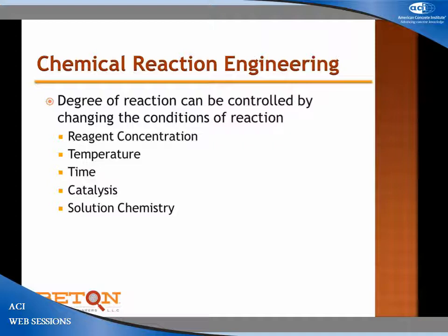So we know all of these things. We know solution chemistry changes because we put gluconic acid in over here. We put a dispersant in over there. We change the solubility of various things to change the reactions already. We just don't talk about it that way. Many materials are not usable as air-entraining agents because their calcium salts are not soluble at high pH. As a consequence, you can have a wonderful salt or wonderful detergent, but if it won't dissociate at 13, if it precipitates at 13, it doesn't really do anything. So we already know some of those things.